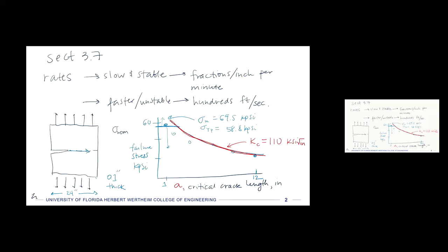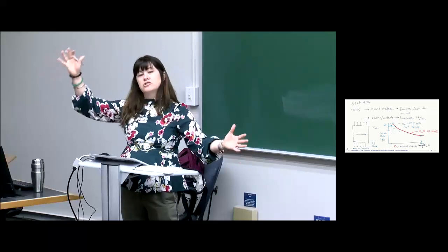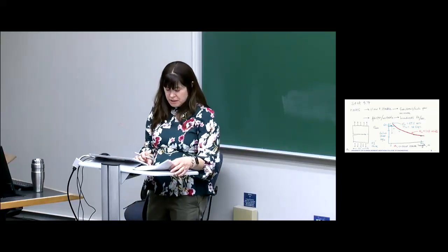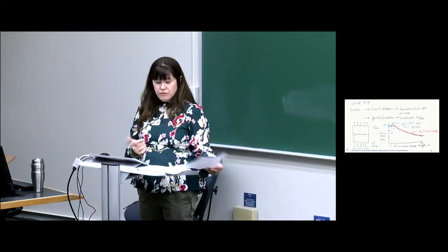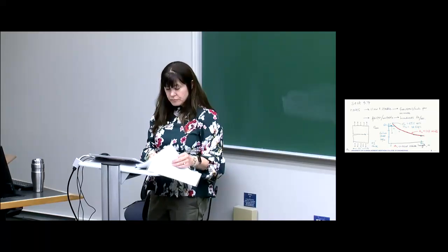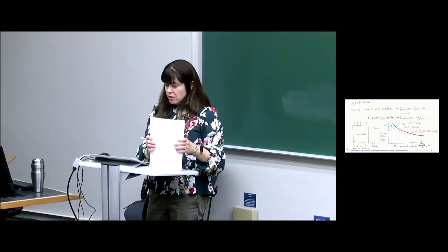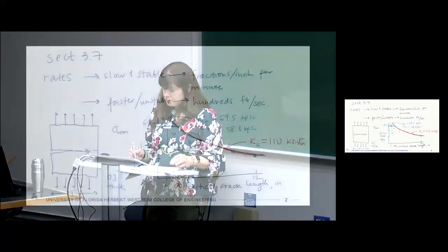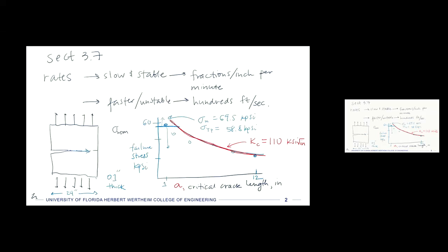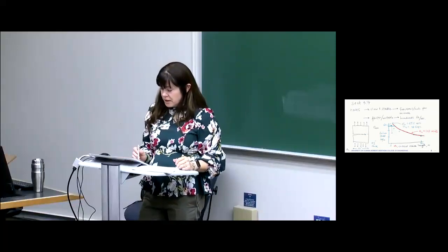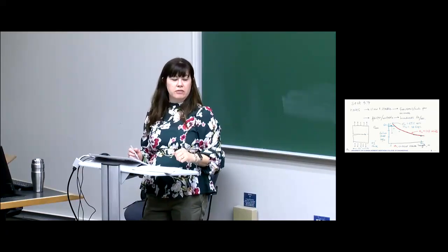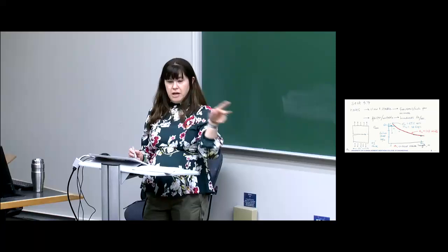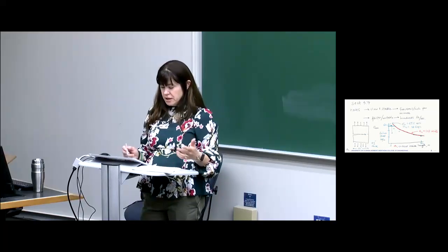But that constant, that fracture toughness, is a material property that you can look up for different materials. Okay? And that specifically refers to how concentrated the stress is at a crack tip in that material compared to the stress in the far field, the stress that you're applying. So that's one way of interpreting that fracture toughness value. So if we go back and think about the setup here of this tensile test, and we think about a crack that's pre-notched in there, right? So we don't care about what the fracture face looks like so far. It's just pre-notched into there. And then we start to pull on this thing.